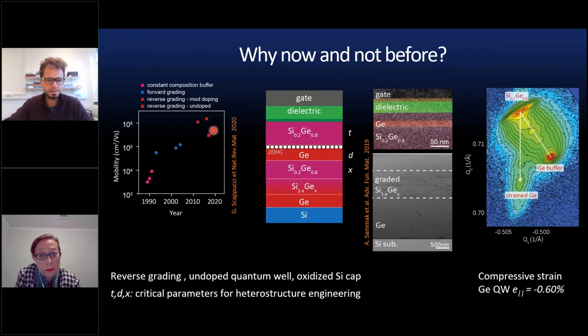And how did that happen? Well, the challenge here with this structure was to get a germanium-rich silicon germanium layer to be a template for the growth of a quantum well. The trick here was to reverse, basically to grow germanium directly on silicon and then grade the silicon into the structure to then achieve a really nice silicon germanium layer. Here you see some electron microscope images of how these structures look. So they are really like you designed them.